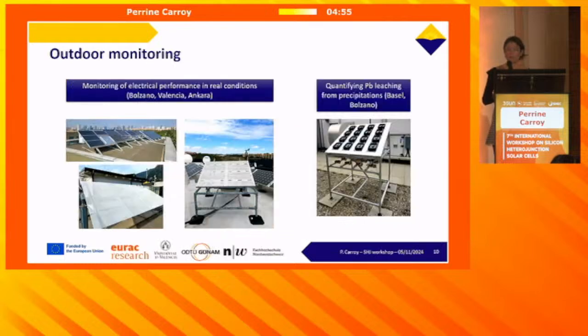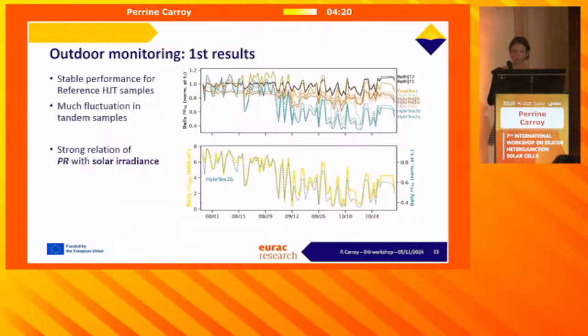And then we want to assess the reliability of these modules in real-life conditions, at 3 places: in Bolzano, northern Italy, in Valencia, Spain, and also in Ankara in Turkey. And we also have special setups to quantify the lead leaching from precipitations. This is done in Basel and Bolzano to see, well, if lead might come from the precipitation that runs on the devices and might contaminate the ground. So we have some first results on monitoring, as we installed a few samples about 3 months ago.